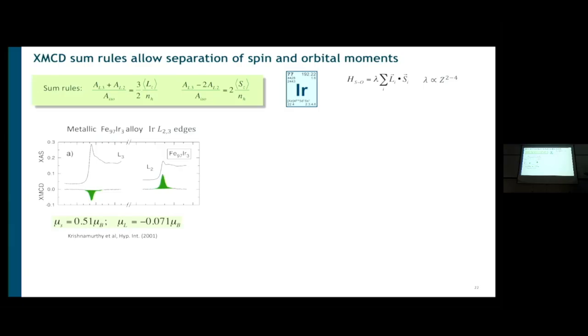If you have a metal and you put a little bit of iridium in the alloy, you have a metal with a very broad 3D, 5D band. The orbital moment is quenched. And you see that the XMCD at the L3 and the L2 have opposite signs and more or less similar areas. And the orbital magnetization is very small, 1% of the spin moment.